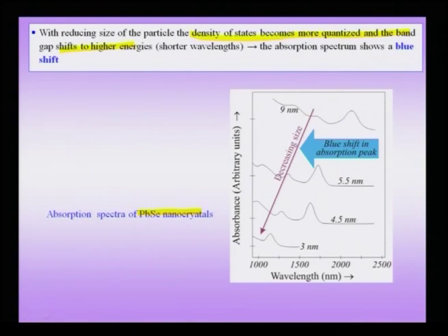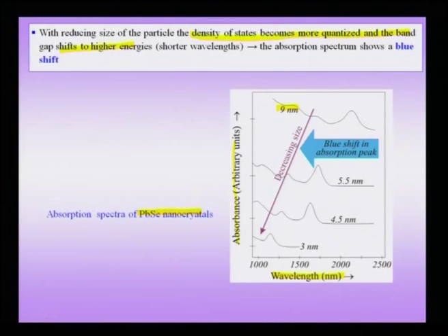In the case of PbSe nanocrystals, again we are plotting the wavelength as a function of the absorbance, and of course, these curves have been shifted vertically so that we can make a comparison, and that is why the y axis is in arbitrary units. We note that there is a dramatic change in the absorption peak as you go from, say for instance, the 9 nanometer particles of PbSe to 5.5 nanometer particles to the 4.5 and to the 3